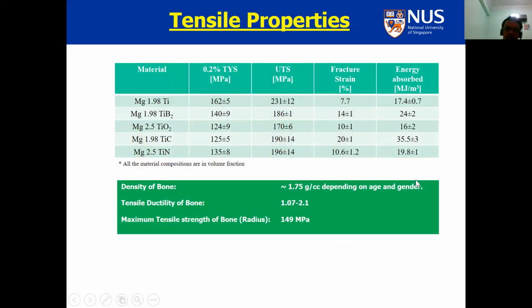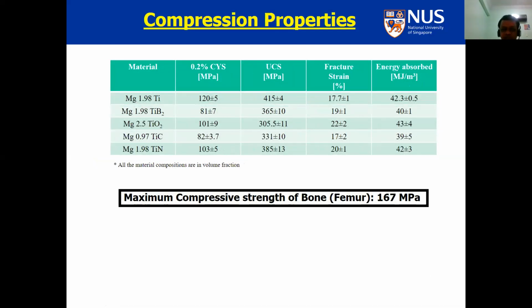So we tried to use nanocomposites, and we tried titanium diboride, oxide, carbide, and nitride. The first thing when you want to use a material is to see whether the properties are superior to that of bone, because we are trying to fix a bone here. The properties of bone are shown in the green box here, 149 megapascal with a ductility of not more than 2.1%. And you see that all the properties in the table exceed that. So first we verified tensile properties, then we verified the compressive properties, which also exceeded much more. That means magnesium is a stronger element because it has both higher strength and ductility when compared to bone.